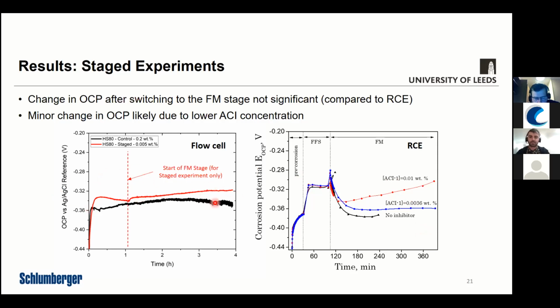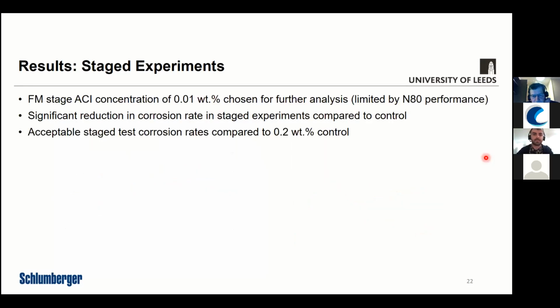And we didn't notice any sort of dramatic changes in these conditions either, which if you look at the RCE experiments, there's some more dramatic differences in the OCP after that initial period. So it gave us some validation to say that our technique was effective for these particular conditions.